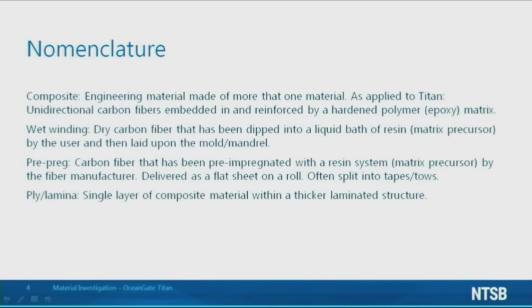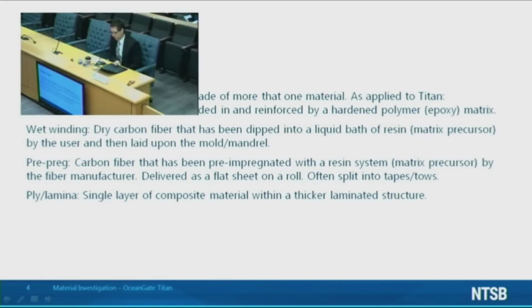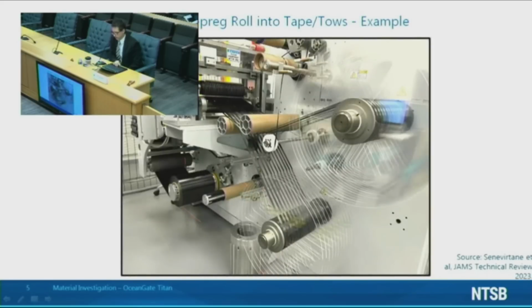The other is pre-preg. In pre-preg systems, the carbon fiber is pre-impregnated with resin by the fiber manufacturer, and is often delivered as a flat sheet on a roll. It can then be split into tapes or tows. Here's an example of a pre-preg splitting operation. This is a comparatively small machine and would probably not have been sufficient for the amount of fiber that OceanGate needed for Titan, but it illustrates the idea of splitting.